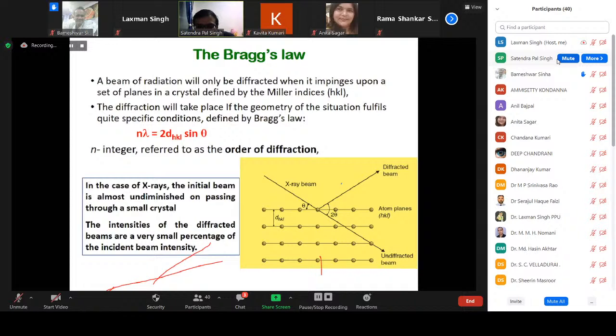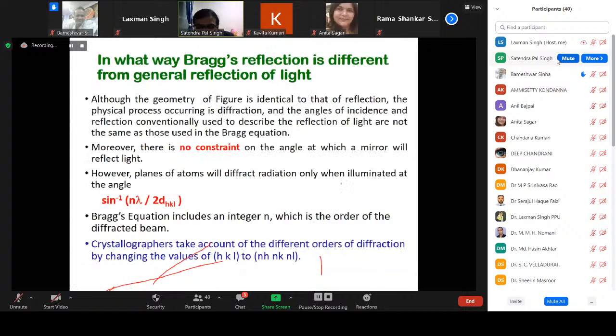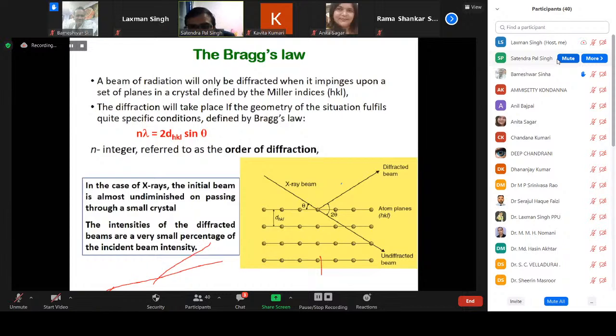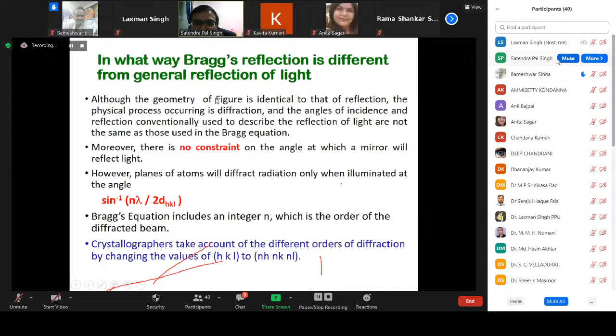Now, in order to understand Bragg's law, the integer n, the order of reflection, is very important to understand. The first thing: if you look at Bragg's law, the angle of incidence is almost the same as the angle of diffraction, and this is similar to the reflection of light. Although the geometry is very similar to reflection systems, it is not actual reflection. This is diffraction, because in mirror reflection there is no constraint on the angles. But in the case of X-ray reflections, there are restrictions on the angles. So there is a particular angle at which the X-ray beam will be diffracted and give a diffraction pattern, and that angle is given by sine inverse of n lambda upon 2d.